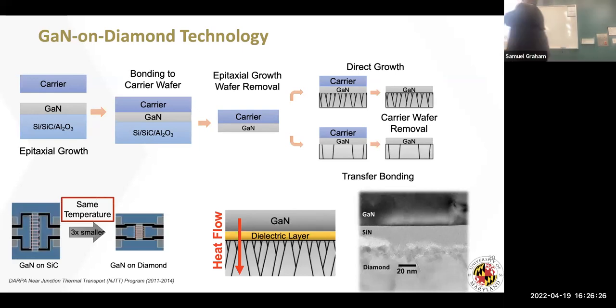So remember before I said I had this silicon nitride, this is the amorphous layer. This is what controls that thermal resistance. When I talked about this large delta between the gallium nitride and the diamond itself. And without going through that today, what we have found is that we have to get this layer down to about 3 nanometers in thickness in order to get the really, really high performance. Again, to try to get to the 5x number, it has to be around 3 nanometers in thickness.